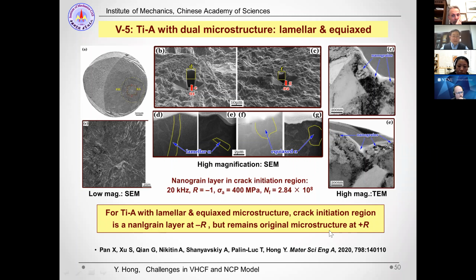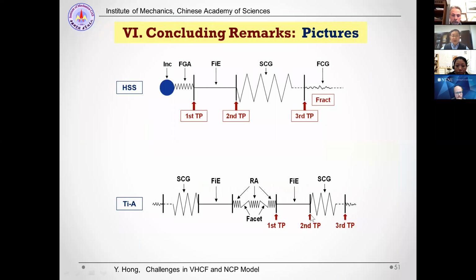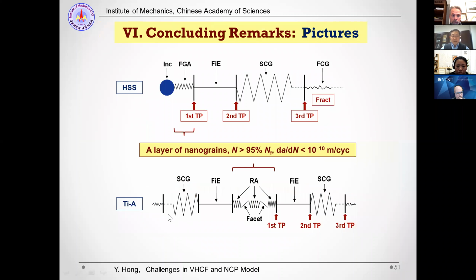So now I would like to conclude my talk. First, I would like to show you again the pictures of high-strength steel and titanium alloy, and I emphasize that the initiation parts are very important: the FGA region for high-strength steel and the corresponding region for titanium alloy, because this part consumes more than 95% of the fatigue life, and also the extension rate is very low.